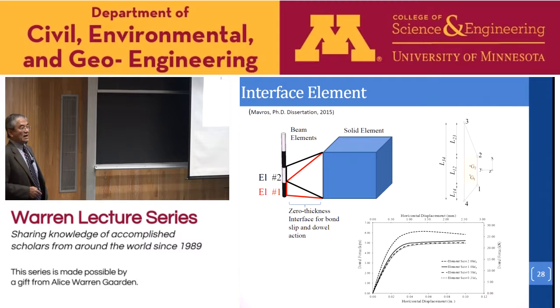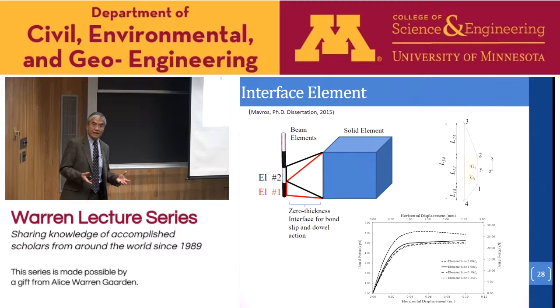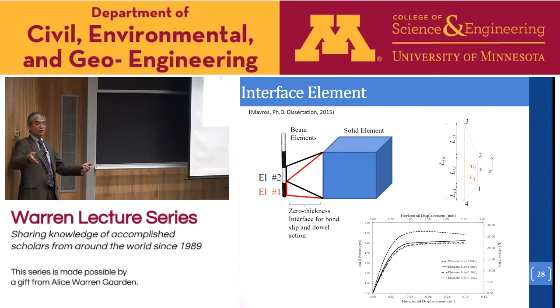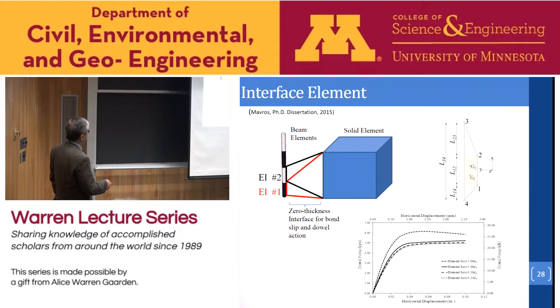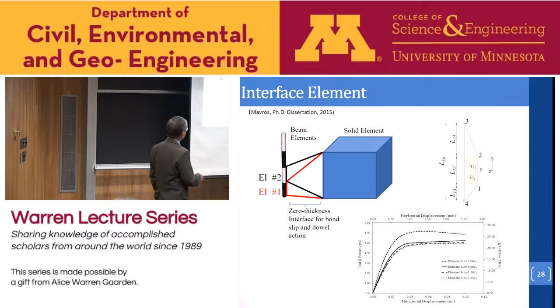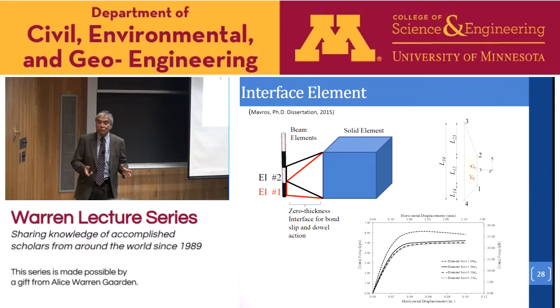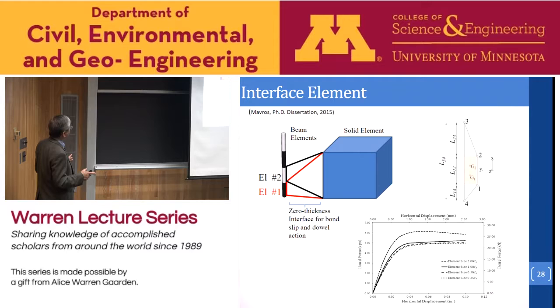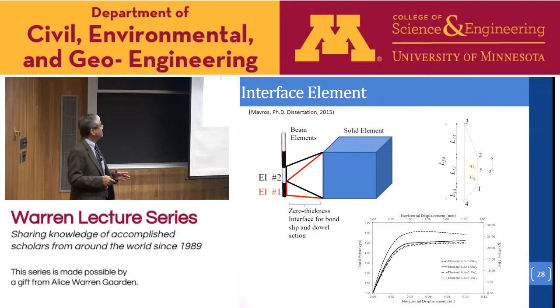Now, to model dowel effect, there can be a number of ways to do it, right? You can model a very detailed 3D finite element model, modeling the interaction of the bar with the concrete, but doing that is computationally very inefficient. You need a very fine mesh. For example, this is based on a simple model study, looking at the sensitivity of the dowel behavior to the mesh size. You can see the solution starts to converge when the element size, the length along the bar, is one half of the bar diameter. So you can see how refined a mesh is required to model this accurately. So really, a detailed 3D finite element model is not a viable approach from the computational efficiency standpoint.